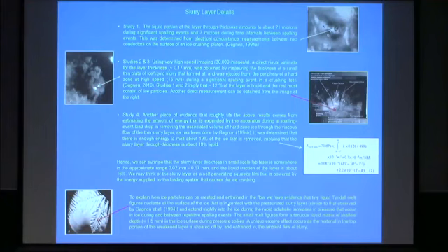I'm about to finish a paper that'll be submitted fairly soon that explains that. Turns out that when you pressurize ice very rapidly, which is what happens during these events, you put the ice into a superheated condition. And when ice is in a superheated condition, and I'm not referring to pressure melting, I'm referring to adiabatic formation of melt figures in the ice. And melt figures are these little features here. The scale on that box is like 2 millimeters across.